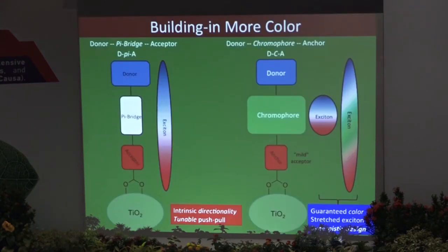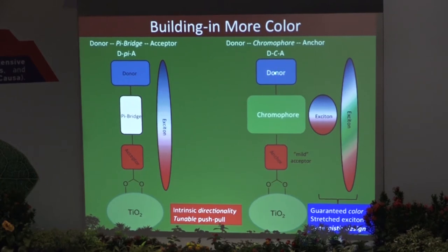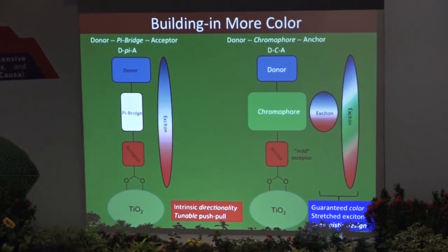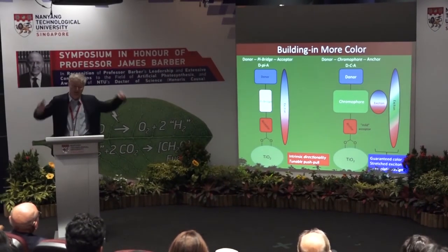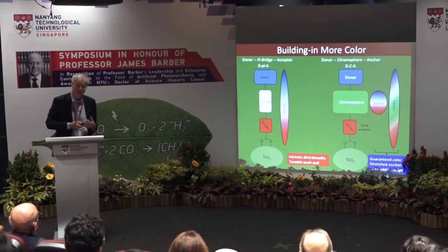Here's our paper in Nature, which made that first for thin film cells. Today, we have these new chromophores or sensitizers that use a donor-acceptor function. Like in nature, we separate the charges by cleverly constructing the dye. When light is absorbed, electrons move from top to bottom, so the positive charge stays up and the negative charge is in the nanoparticle. That sets up a spatial separation between negative and positive, so charge separation lasts for milliseconds or even seconds before charge recombination — giving us a chance to collect those charges.